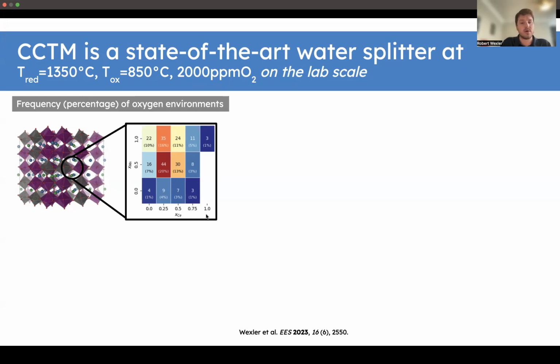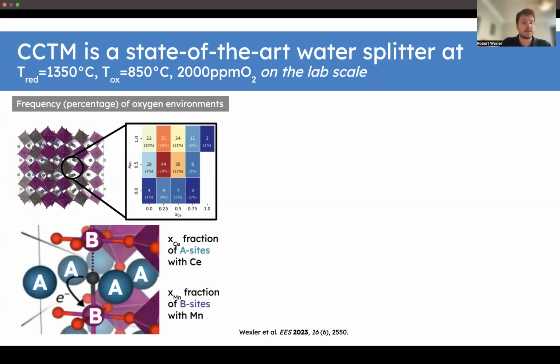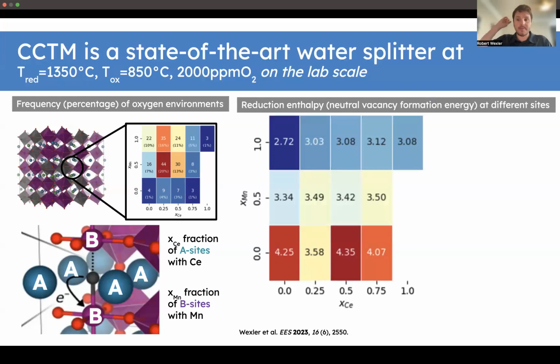The x-axis shows the fraction of ceria, and the y-axis, the fraction of manganese surrounding the vacancy on the A and B sites respectively. So just to give you a better intuition for those, each vacancy shown here in black has 4 A site neighbors and 2 B site neighbors. The fraction of ceria on these A sites is X sub Ce, and the fraction of manganese on the B site is X sub Mn. So here are the reduction enthalpies for neutral oxygen vacancy formation energies at these different sites that we considered.